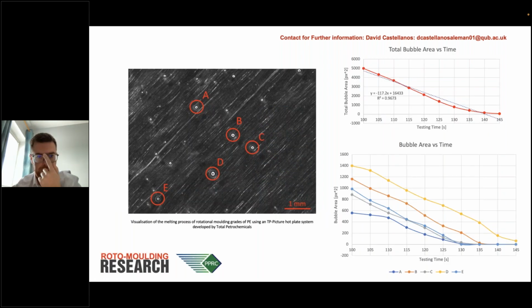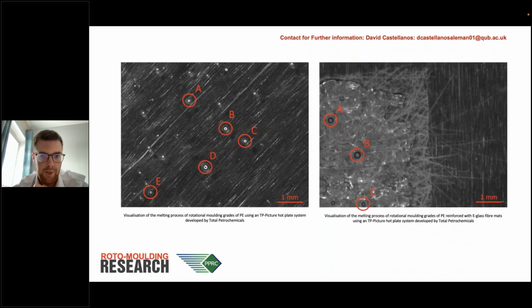He then went on to understand the relationship between the bubbles, the pinholes that remained within the polymer melt after you put in the composite reinforcement. So he was using the same technique that I was using to monitor bubble sizes in polymer melts. And here's an example of what that would have looked like. So on the left-hand side, you've got the bubbles in just a standard rotational molded polymer melt. And on the right-hand side, you've got bubbles that are suspended above the composite reinforcement. So there was some work involved in trying to optimize that to make sure that the pinholes were removed during the cycle.